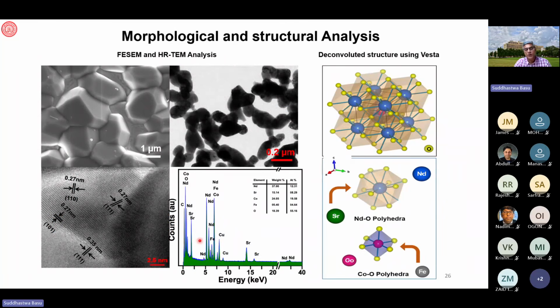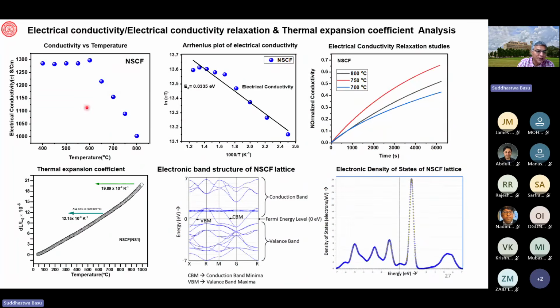And that is how, by doping, we felt that we would improve the oxygen conductivity and, as a result, the cell performance. Here again, we are showing you the same NSCF structure, and then you have the doping. And so we have NdO polyhedra and cobalt-oxygen polyhedra formation. And here the EDAX and the lattice spacing, everything tells us that we could make the iron and strontium doped neodymium-cobaltite.